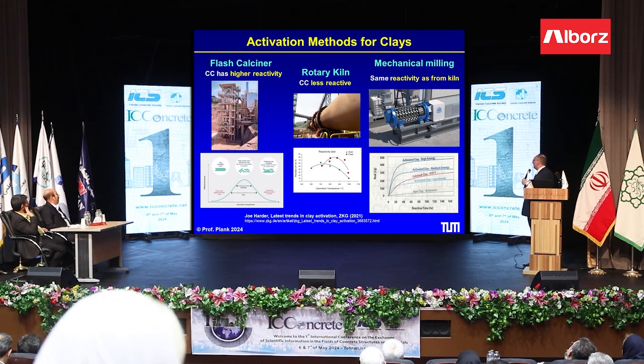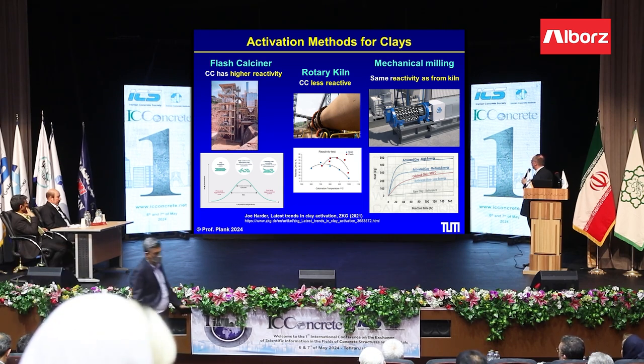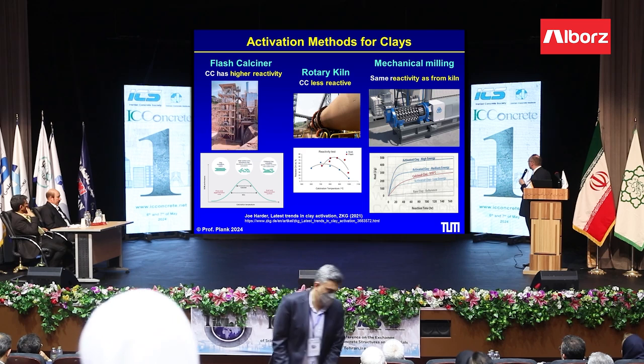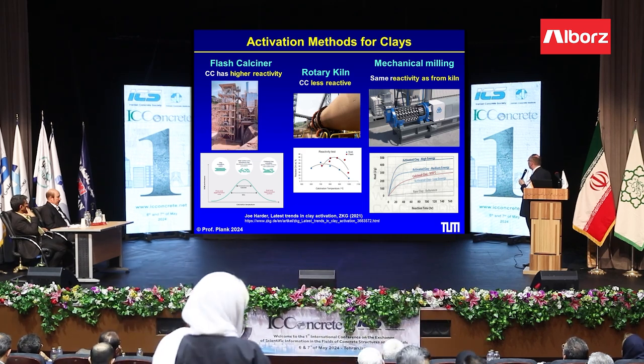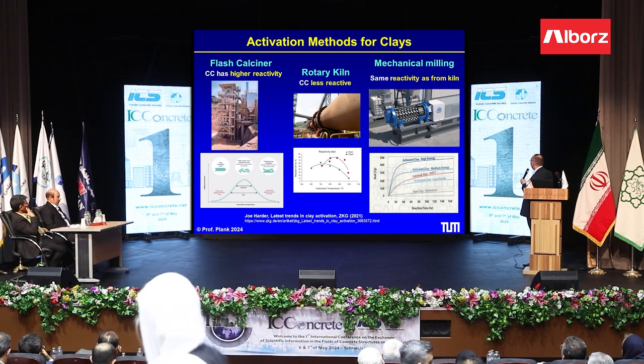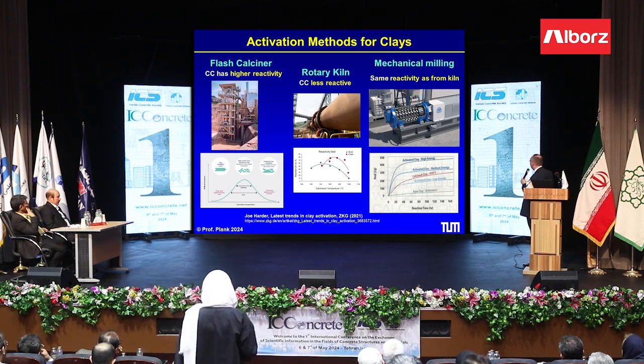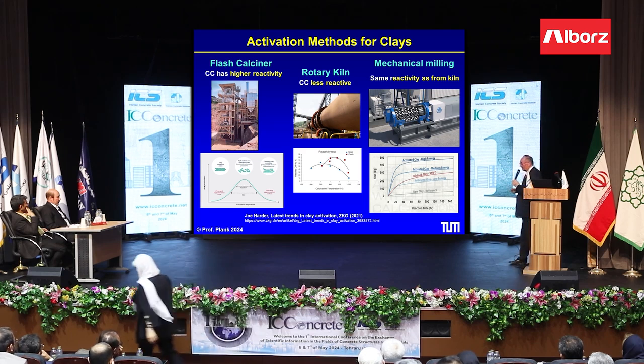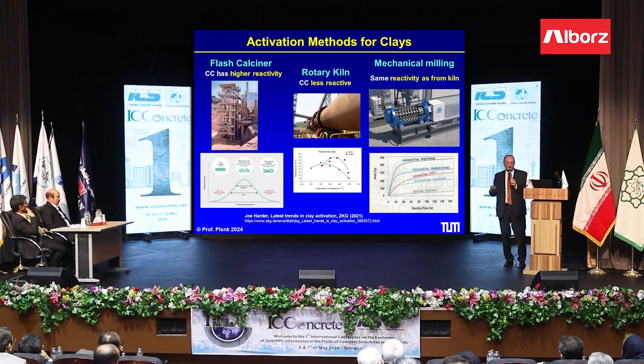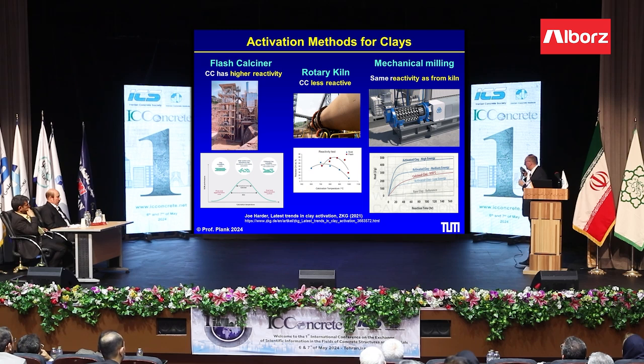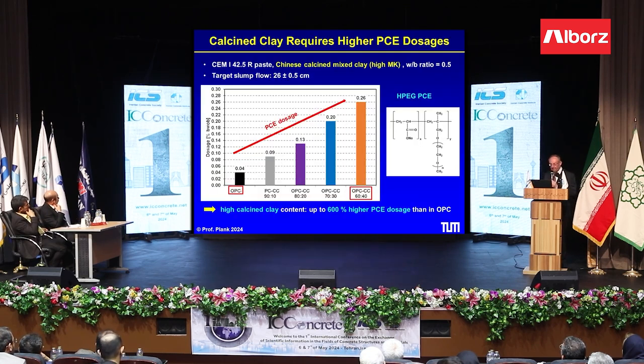Now, calcined clay, there are different ways to do this. In a flash calciner, it gives the highest reactivity of the calcined clay. In a rotary kiln, maybe this is more convenient, but the reactivity is a little bit less. And very recently, ThyssenKrupp introduced a mill where you take the raw clay and you just mill it. And by milling, you mechanically activate the clay. It's the cheapest way and the most convenient way to have activated clay as a clinker replacement.